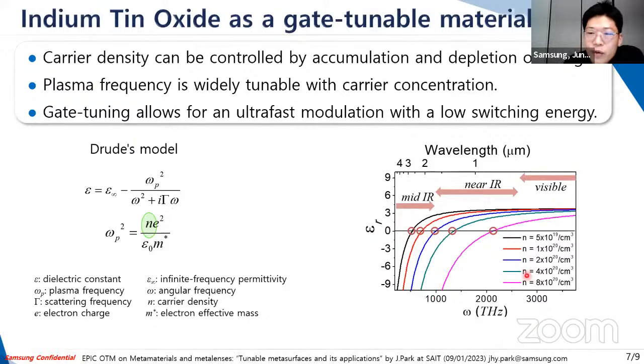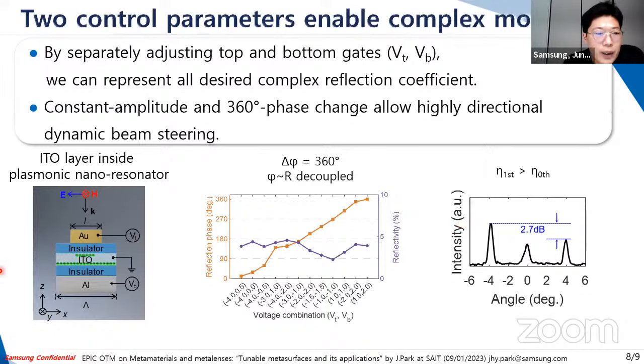And as you can see from here, by changing the gate carrier concentration by external gate, we can tune the dielectric constant in a very wide range. And we put this active material of the indium tin oxide sandwiched between the top and bottom metallic antenna here, and we connected the separate applied bias, V sub T and V sub B. By using various combinations of the voltage of V sub T and V sub B, we can actually achieve the 360 degrees or full 2 pi range with the reflectivity and phase fully decoupled here.